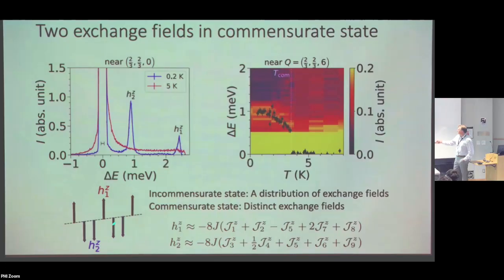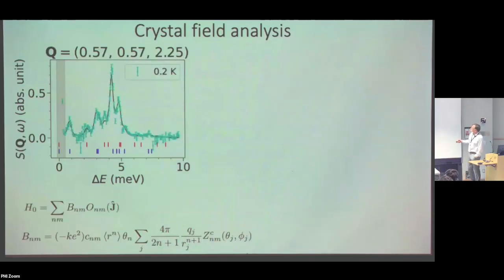The upspin has always two antiparallel spins surrounding it. The downspins always have both an upspin and a downspin surrounding it. So they have different fields, and this will be the exchange field associated with this side. That's the exchange field associated with the majority spin side. And those get related to the Z component of the exchange interaction in this particular way. And I have to define which, the numbering, etc. But we have a long-range interaction, so we have to keep track of a whole set of different exchange constants. Okay, so then we have to actually, in order to determine the exchange interactions, we need to also know the crystal field Hamiltonian, and that has to all sort of be simultaneously in a consistent manner analyzed.